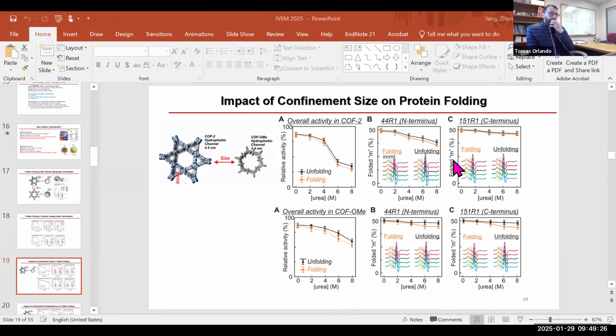Yeah, so, good question. For example, if I want to fold the protein, I unfold it using 8 molar urea, load it into the MOF, which was also incubated with 8 molar urea, so it's completely unfolded even inside, and I measure EPR. Those I can do 5-10 scans, about 3-5 minutes.